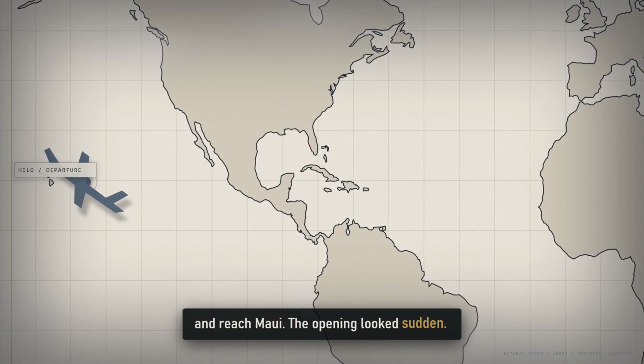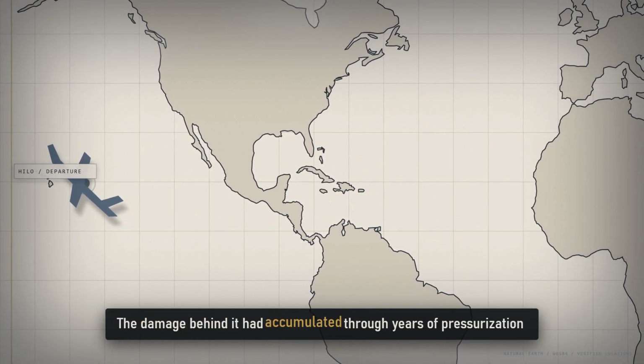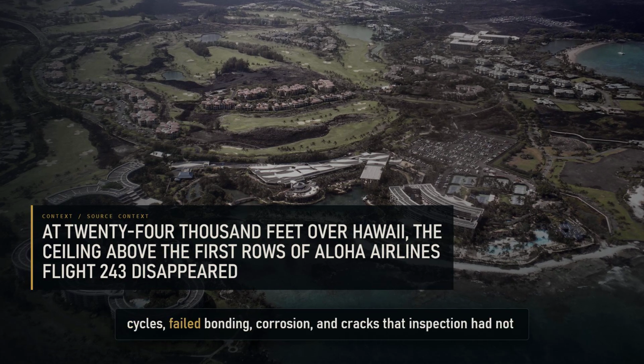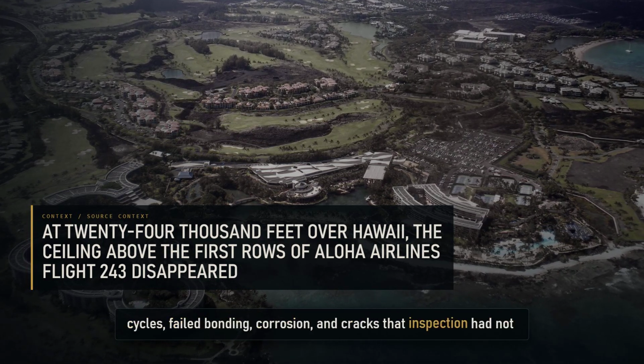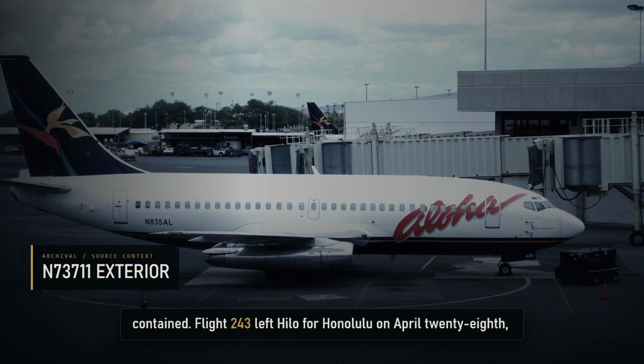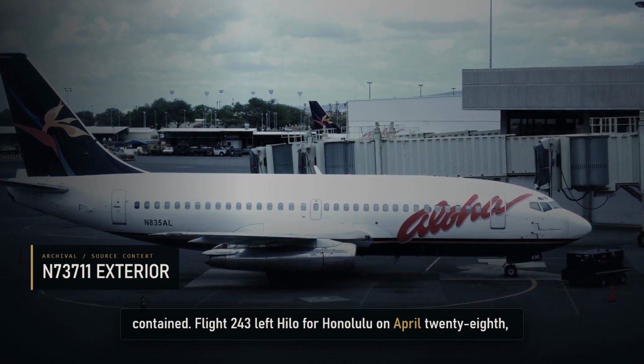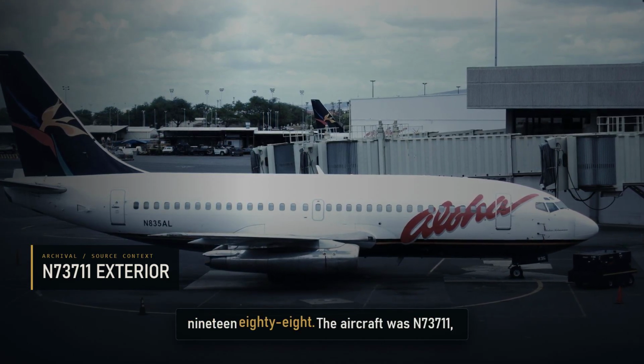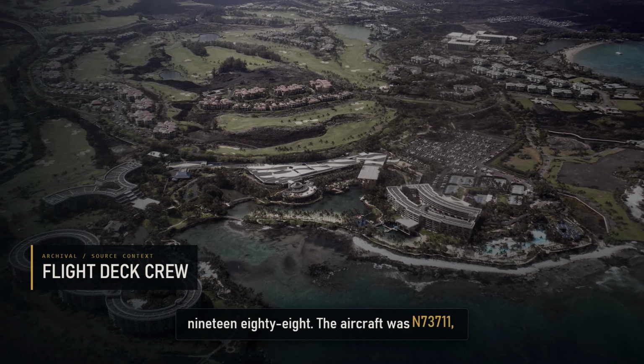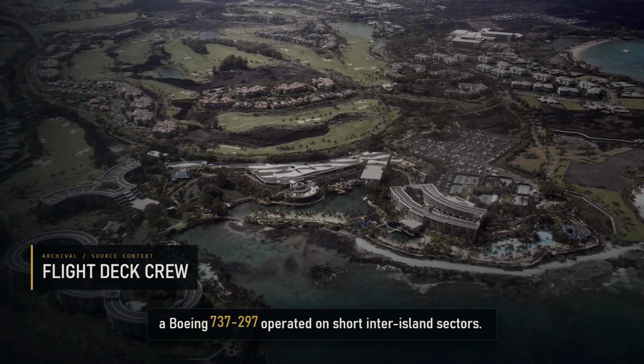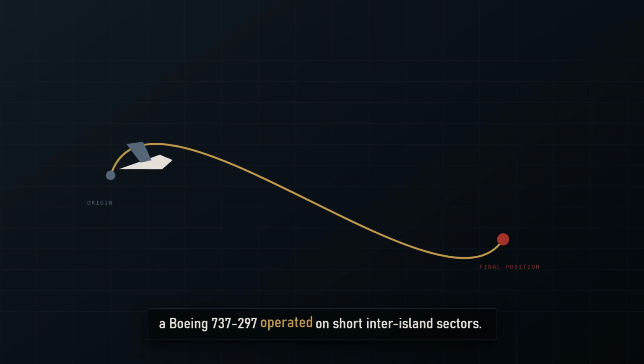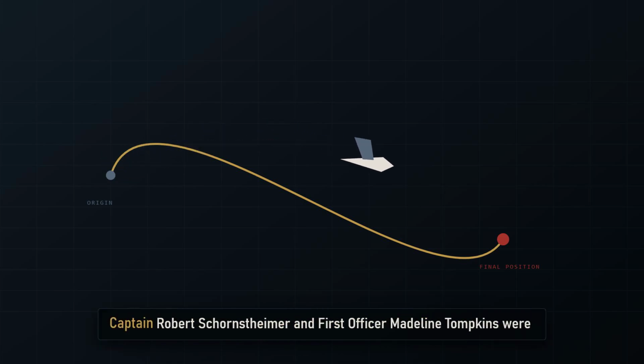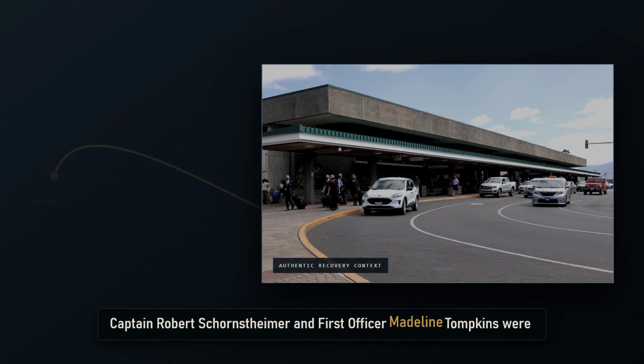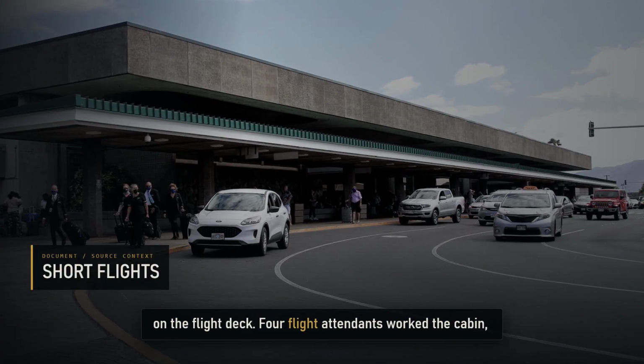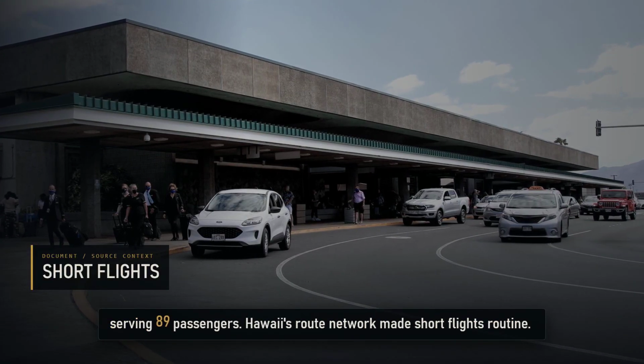The opening looked sudden. The damage behind it had accumulated through years of pressurization cycles, failed bonding, corrosion, and cracks that inspection had not contained. Flight 243 left Hilo for Honolulu on April 28, 1988. The aircraft was N73711, a Boeing 737-297 operated on short inter-island sectors. Captain Robert Schornstheimer and First Officer Madeline Tompkins were on the flight deck. 4 flight attendants worked the cabin, serving 89 passengers.